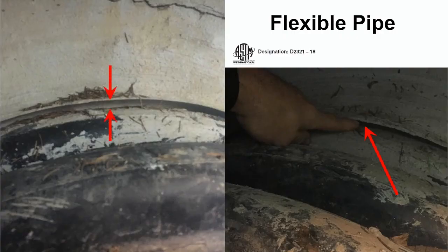ASTM D2321 also addresses manhole conditions as well. This photo shows an installed manhole with a 36-inch diameter HDPE pipe grouted in. The contractor called the manhole manufacturer and said that the manhole was leaking. When they investigated, they learned that the pipe had pulled away from the grout.